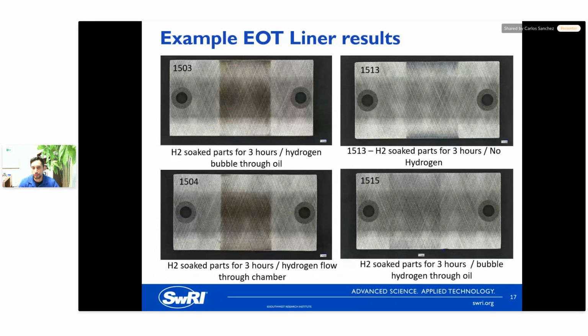Looking at the wear, like I said, one of the critical things in doing a ring liner test is the alignment. So you can see we have pretty good alignment on all of our tests. There's no edge loading, no center loading. It's fairly even wear across all surfaces. When doing the more severe cases with hydrogen, you can see that there's a little darkening of the surface. So most of this is all abrasion. There was a question earlier in the previous talk, what type of wear are you seeing? Mostly it's going to be abrasive wear. We did also look at SEM and EDS images or measurements of these surfaces, and we didn't really see any embrittlement or any sort of damage related to hydrogen. It's mostly what you would see for just typical abrasive wear for a ring and liner environment. Just in the hydrogen case, it's a little bit more severe. It's more like running the test for a longer period or at higher loading than normal.